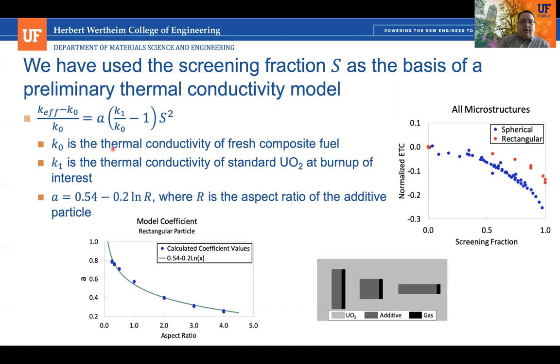So that's what this A parameter is for. And we just fit it, but we don't fit it to the data. We want to be able to compare against the other simulation results that we've already shown you. We're just going to fit against very simple microstructures where we just do rectangles, and we're just changing the aspect ratio in the direction of heat transport of the additive. And we have the gas just being a rectangle. And we fit to that to get our fit for A. So we've calibrated this geometry coefficient that describes the geometry of the additive.